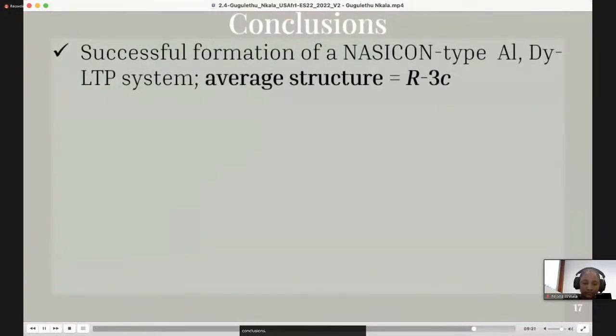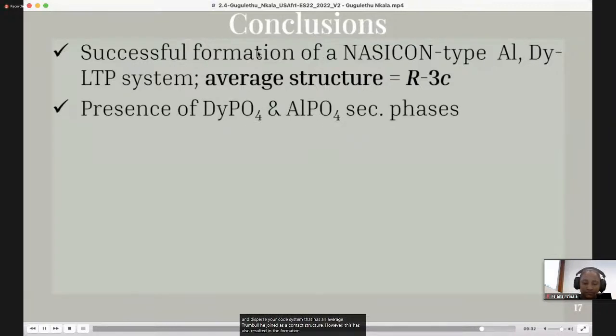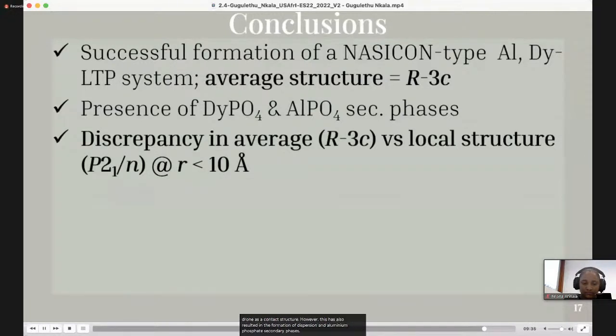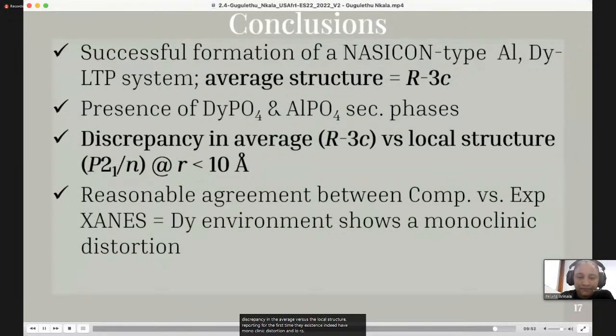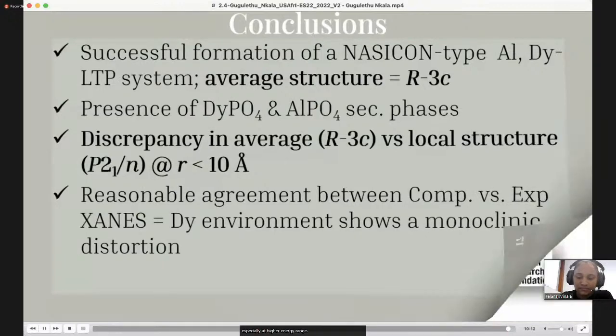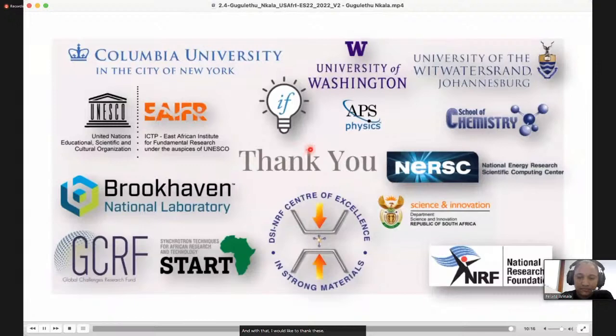Our conclusions: we have successfully formed an aluminium and dysprosium co-doped system that has an average rhombohedral NASICON-type structure. However, this has also resulted in the formation of dysprosium and aluminium phosphate secondary phases. Pair distribution function small box modeling has shown a discrepancy in the average versus the local structure, reporting for the first time the existence indeed of the monoclinic distortion at low R. XANES has shown a reasonable agreement between our computational and experimental data, which supports the existence of dysprosium in a monoclinic environment, as only one phase, a secondary phase, does not fully account for our experimental data, especially at higher energy range. And with that, I would like to thank these organizations and thank you for your attention.